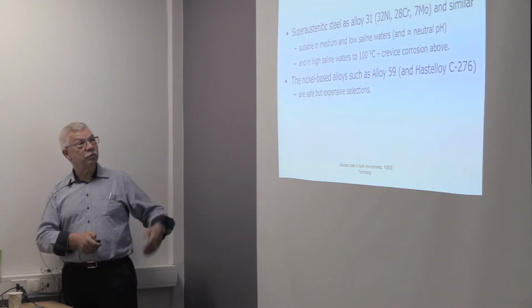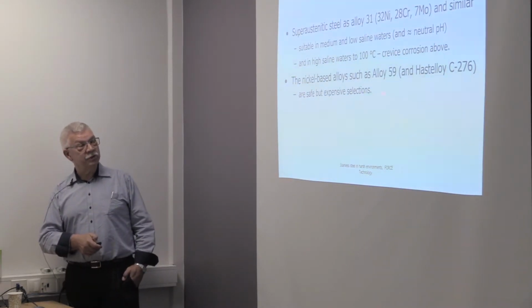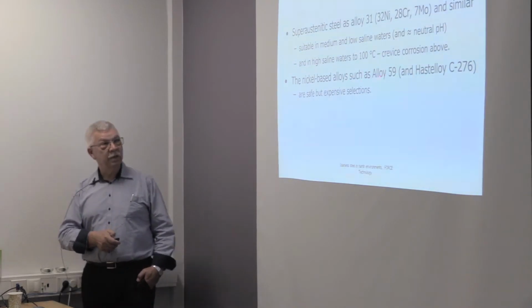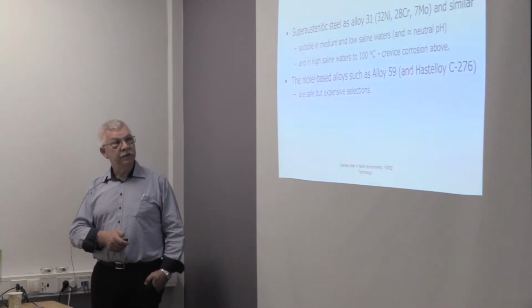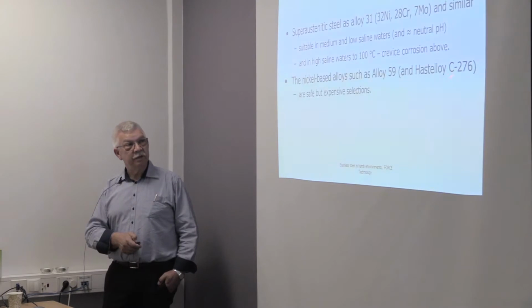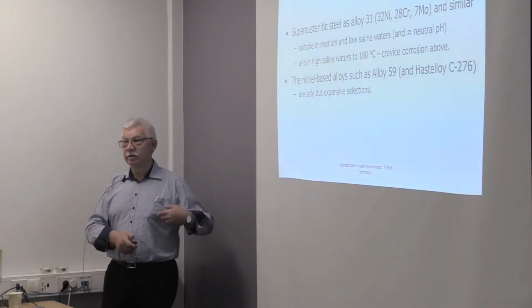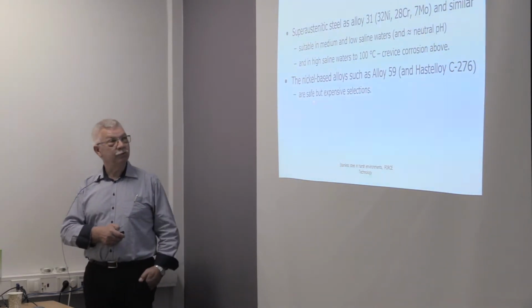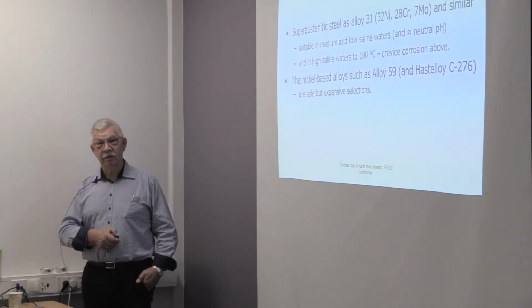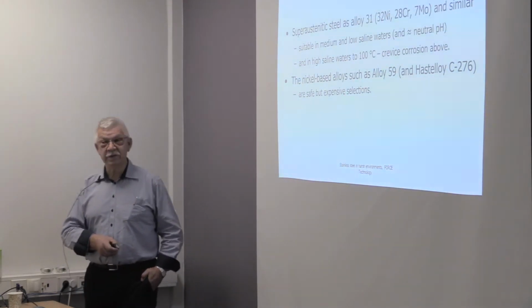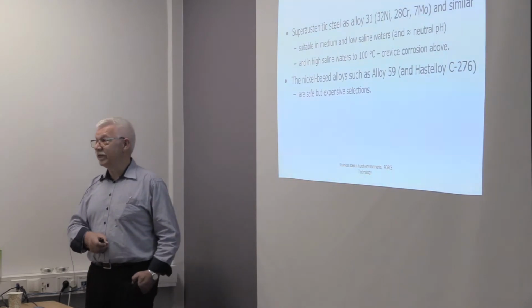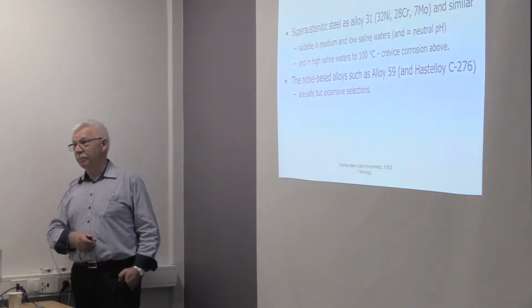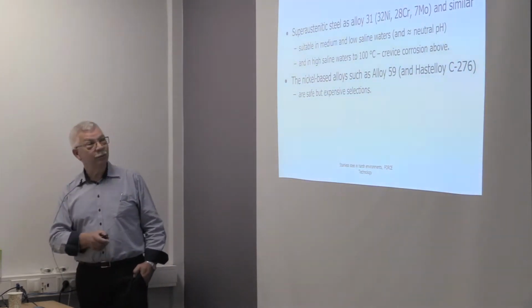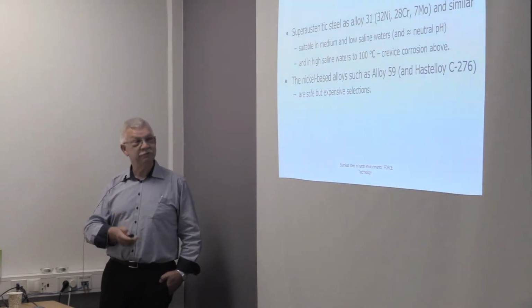But of course, you can choose higher alloyed, more resistant materials like the nickel-based alloys, alloy 59, Hastelloy C276. They would be perfectly safe, but also very expensive. Perhaps 10 times what you would pay for a stainless steel per kilo. So it will be expensive to be safe.